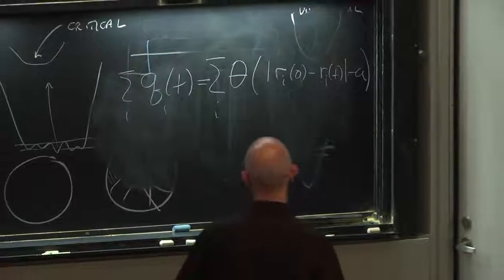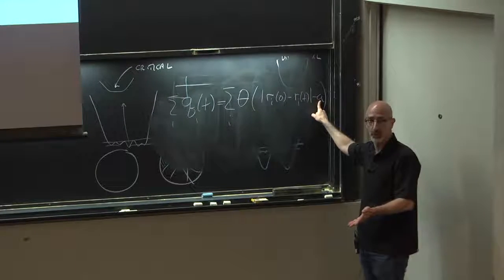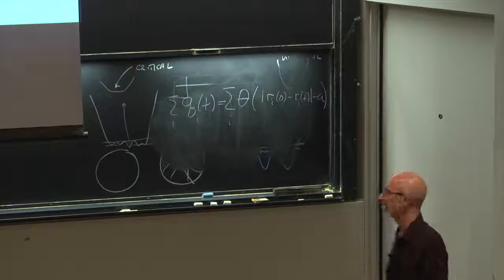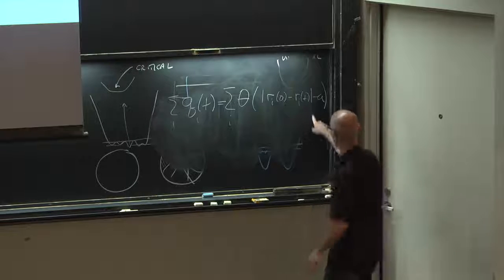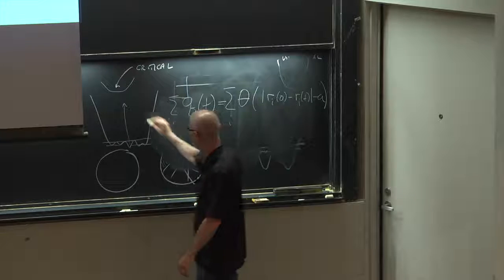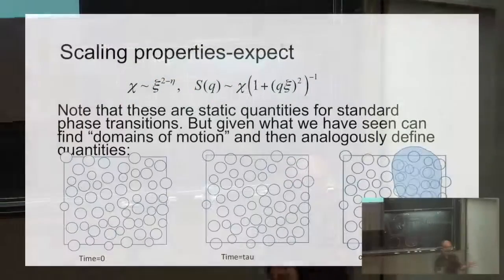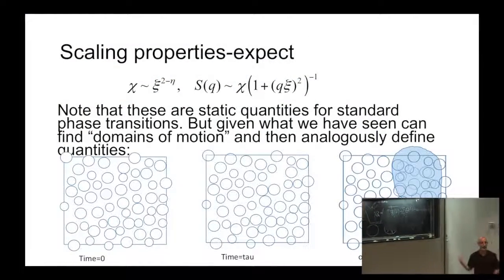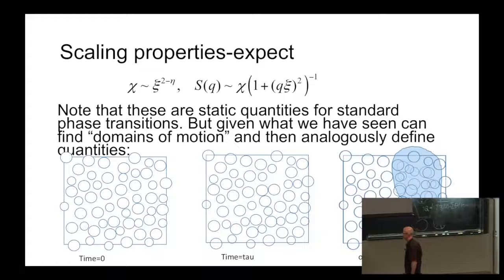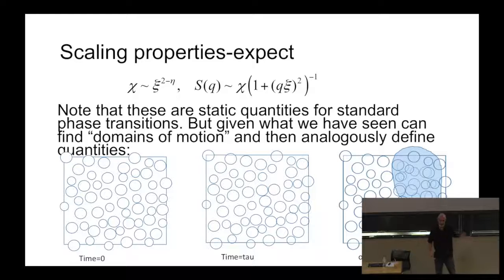And we have to set what this length scale is. The answer is going to change depending on it, just like in the Weeks and Weitz movie, we have to set a threshold for when we say a particle has actually jumped or not. And that's going to change the answer. We also have to pick what time scale we care about. But then we could look at the fluctuations of this parameter Q, and presumably if there's something critical in the dynamics, the susceptibility on some time scale and length scale associated with this parameter is going to grow and grow and grow like it did in the Ising model. And I'm going to be able to extract a length scale from that by just generalizing what I did for the Ising model to this overlap function.